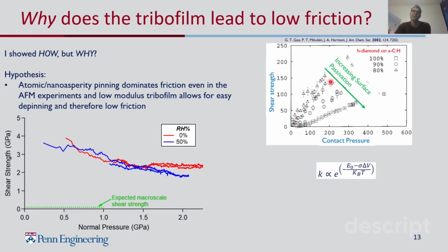They prepared this system such that it was deficient in surface passivation by only passivating 80% of the surface bonds. And in that case, they have a very positive slope of shear strength versus contact pressures. But as they increase the passivation by increasing the hydrogen at the interface, what they see is that the slope goes down and becomes more flat. So let's compare this to an example where there's no interfacial bonding.